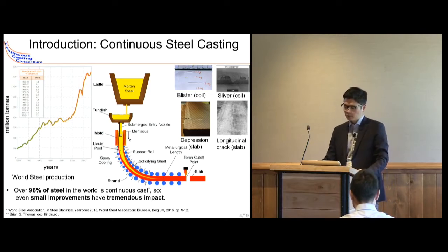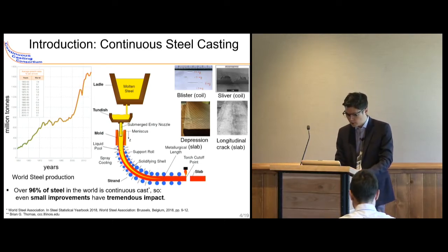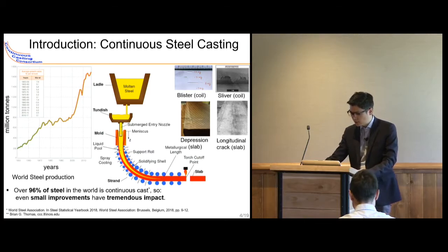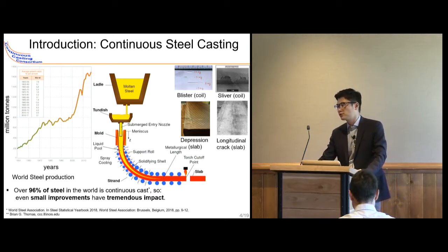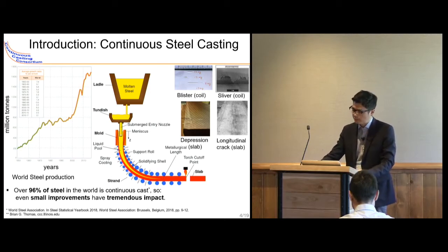In the continuous casting process, molten steel flows from the ladle through the tundish into the mold. It should be protected from exposure to the air by a slag cover over each vessel and by ceramic nozzle between the vessels. Also in the mold, the molten steel freezes against the water-cooled mold plate wall to form a solidifying steel shell. This shell contains the liquid fraction as the shell is withdrawn continuously from the mold bottom region.